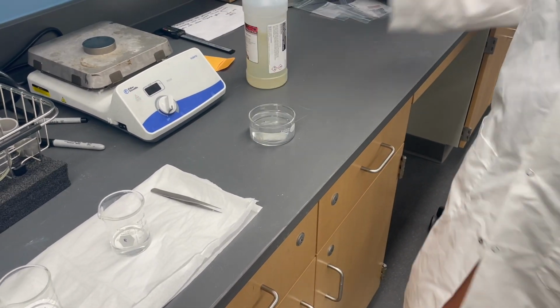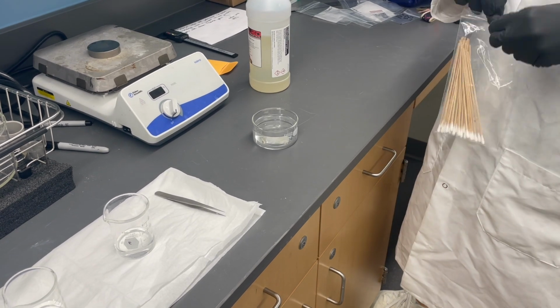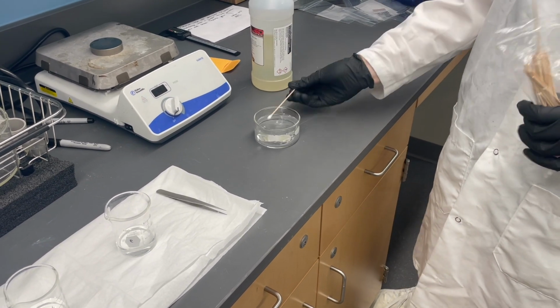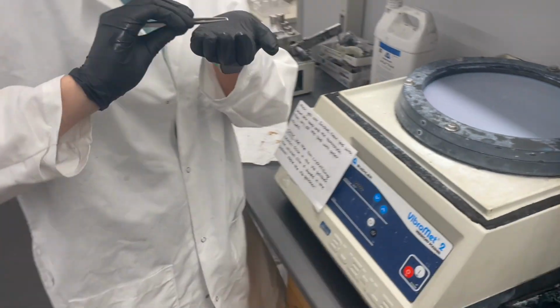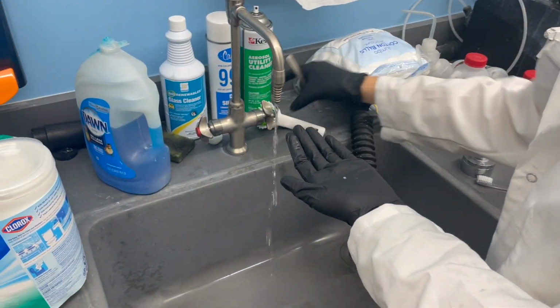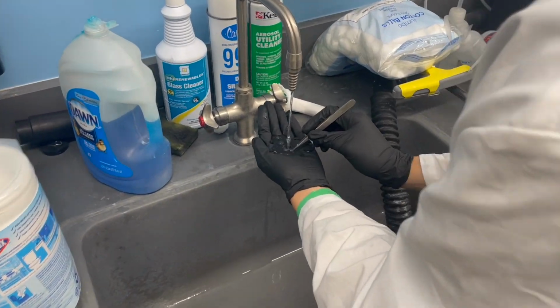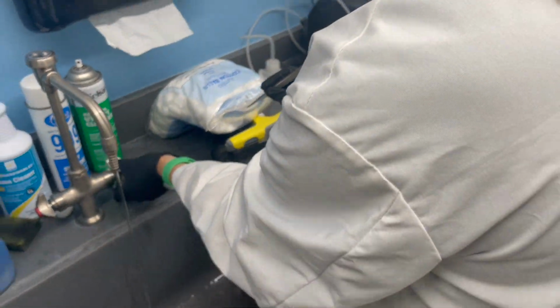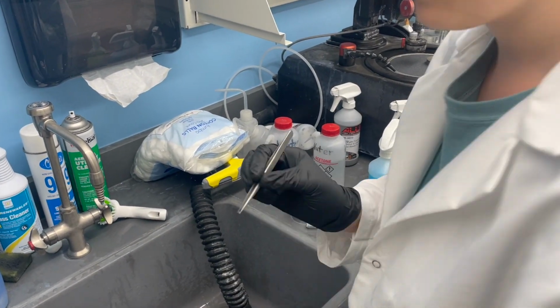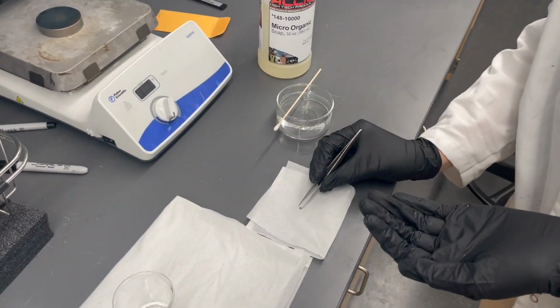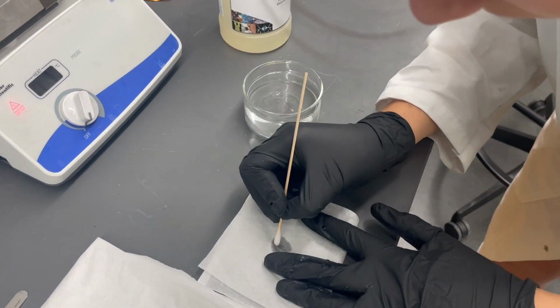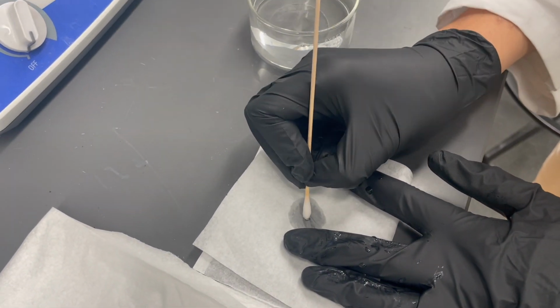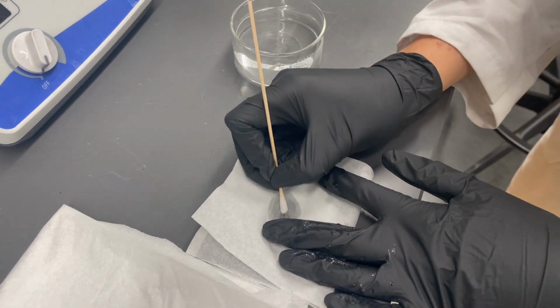Fill another dish with water and Micro-90 soap, mixing with a cotton swab. Use the tweezers to take the sample out of the acetone and place it polished side down in the colloidal silica left in the vibratory polisher and gently move it around using your finger. Then bring it back to the sink and gently rinse with water. Place the sample polished side up on a Kimwipe and use the cotton swab from earlier to scrub the sample surface with the Micro-90 soapy water.